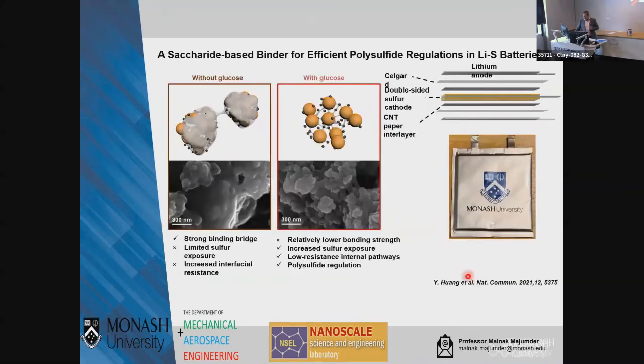Our work, again published last year, where we were able to incorporate glucose into the cathode system, which has also catalytic properties, and also modifies the viscosity so that you can make these kinds of interesting architectures. We were able to produce these pouch cells. I'm very happy to let you know that in our labs, we are able to produce almost 2 amp hour batteries, and energy densities are about 350 watt hour per kg, which is probably one of the best in the world at this point of time.